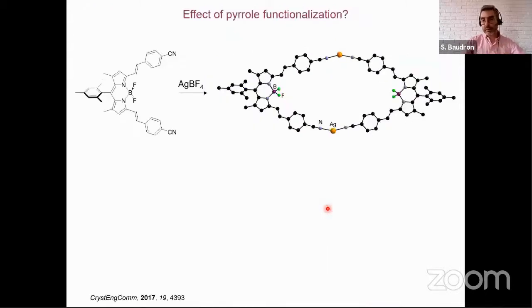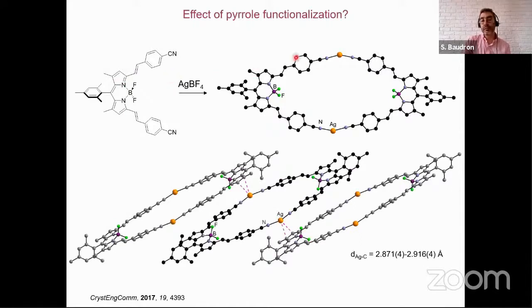So we went on to see whether we could generalize that to other types of systems, and not only metal complexes, but also BODIPY derivatives, and also see whether the functionalization at the periphery could have an influence. So Fan Zhang prepared this BODIPY derivative, bearing here a methyl group, and assembled it with silver(I) cation. We obtained 2+2 metallamacrocycles, and those metallamacrocycles stack in the solid state by a silver-pi interaction, or at least let's say that there is a silver-carbon distance that suggests this interaction, with a distance of 2.8 to 2.9 angstroms. So it is interesting to see that even in this case where we have a methyl group, the interaction that we observe, or the mode of assembly, always involves the carbon-carbon bond, what would be the equivalent of the beta-pyrrolic carbons for a porphyrin.